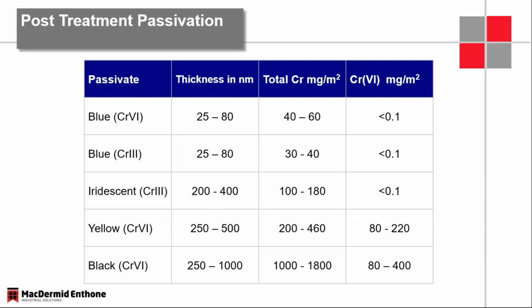So I was talking before about the film thickness, and you can see that a hexavalent blue chromate is about 25 to 80 nanometers. Chrome content in milligrams per square meter is on the lower side, as is just chrome metal. Trivalent blue chromates, your decorative blue type of passivates, are going to be similar in thickness and in chrome content. When we really start building a much thicker film, now we're starting to get into higher corrosion resistance. The iridescent trivalent passivates, 200 to 400 nanometers as mentioned. And then the older school yellow hexavalent iridescent are going to be similar in film thickness, but obviously they're going to have much more chrome in them.